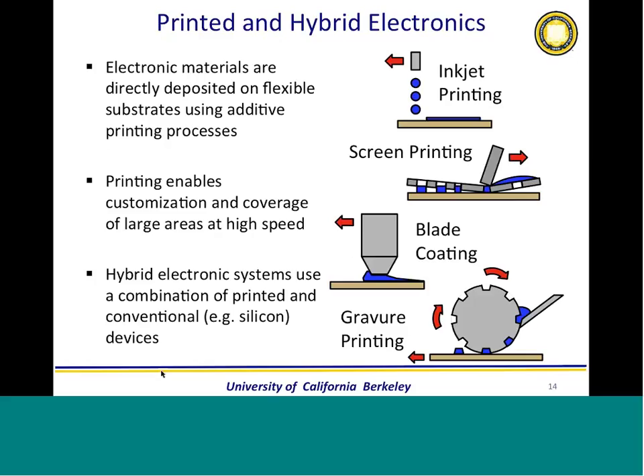And there are formulations for screen printed silver. There's formulation for inkjet printing. There's all sorts of formulations of ink that you can buy by the bucket, which is great. And then one of the criticisms that silver nanoparticles or metal nanoparticles had, especially when you think about roll-to-roll manufacturing, was that you have to anneal the material. You have to sinter the nanoparticles in order to have the conductivity that you want. And those methods are mostly thermal annealing.